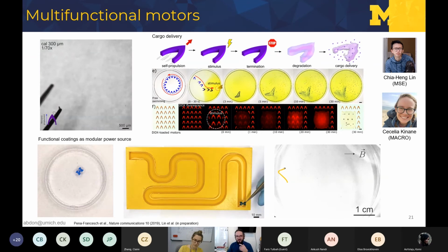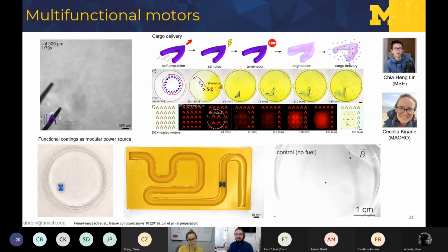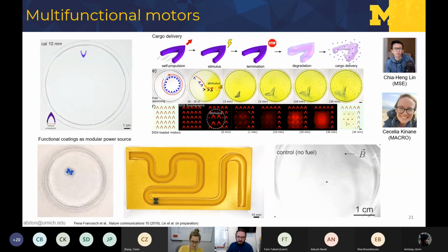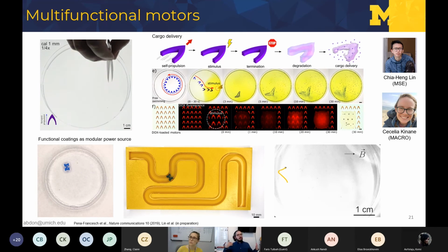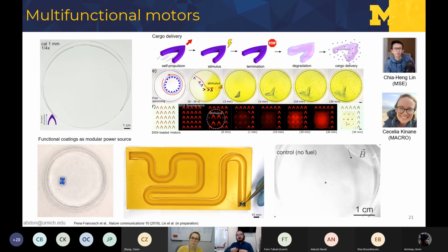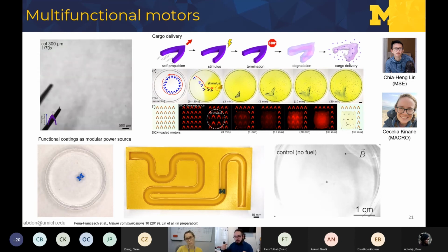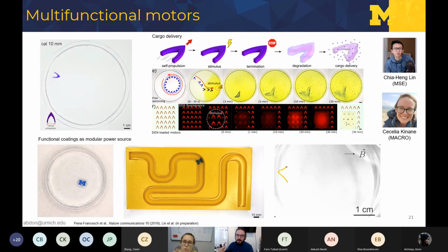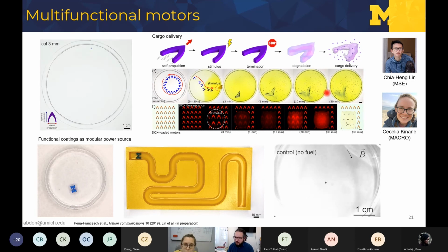But again, what we wanted to do is explore some new functions that other materials don't have, right? And because we can dissolve this protein and cast it, and it's very versatile in the fabrication, we can also embed some drugs for cargo and drug delivery for this, right? So as you can see here, we have these little motors spinning around, but loaded, in this case with a dye, but we loaded with drugs and with some other molecules just for testing. But you can control their locomotion by giving some external stimulus. In this case, it's pH that can open up the porosity of the material, right, by breaking these beta sheet structures. So you can open it up so this dye is released over time, so you can use it for controlled, on-demand stimulus-responsive delivery of many molecules.